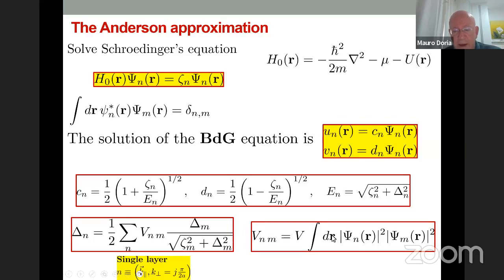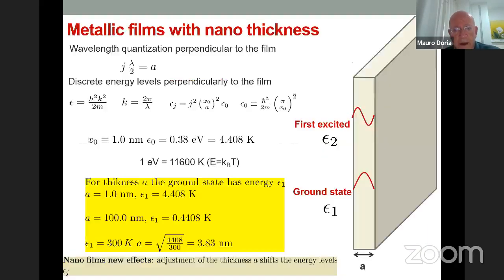And in fact, you have a potential energy and the electrons in different levels. So, for instance, if you go back to the metallic case, we know we have a ground state like this. In the film, we have excited states, all satisfying this rule, j lambda over 2 is equal to a. A is the thickness. The discrete levels are given by this free particle expression. We feed this into that wavelength, and we find that the energy levels are a discrete number squared, and there is some basic energy.